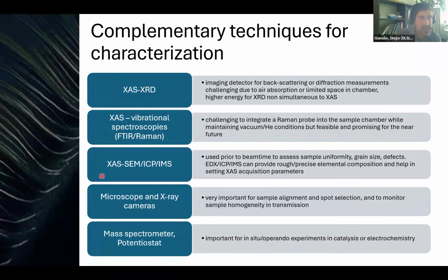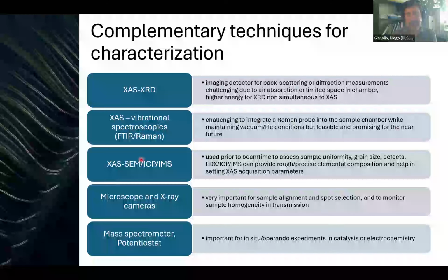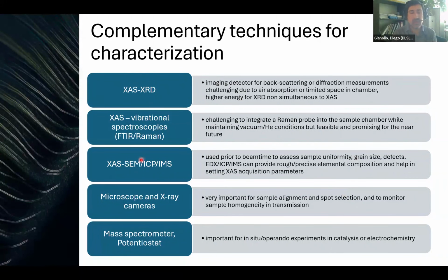The other techniques mentioned here are more techniques to characterize the sample, possibly prior to the measurements, in order to optimize the measurement conditions. So, for example, SEM, ICP, and IMS can provide a rough or precise elemental composition. It would be useful to assess also the sample uniformity, grain size, and defects, and this will surely help in setting the XAFS acquisition parameters. In particular, if you then want to do a mapping of the sample, you could first have an overview with one of these techniques and then go into a more specific point with the